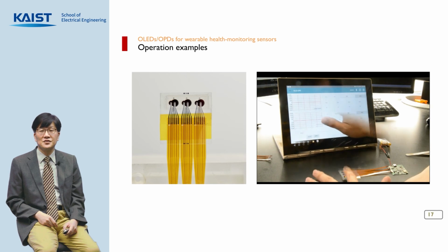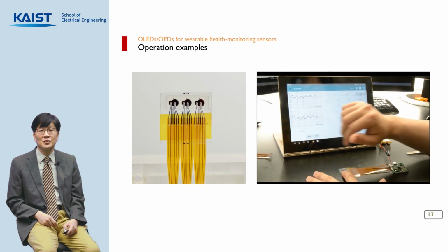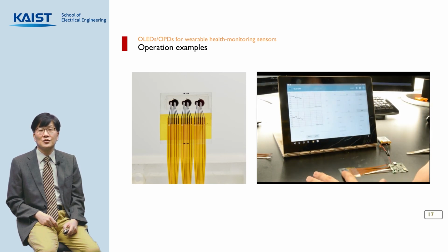This is another photograph of the actual sample we fabricated. The overall devices were encapsulated with PET with embedded barrier films under a face seal geometry. And interconnecting electrodes for connections were done with ACF, or anisotropic conductive films. You can see here on the right side the actual operation of our pulse oximeters. A custom designed circuit board was used in collaboration with Professor Hoi-Jun Yoo's group in our institute.